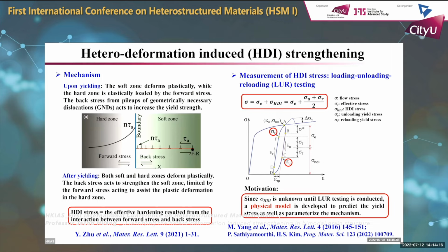In practice, the contribution of such HDI stress to the overall flow stress can be estimated by the loading, unloading, and reloading (LUR) testing. But in this study, we have some motivation. We still think it is necessary and meaningful to develop an analytical dislocation model with more physical meaning to predict the yield stress as well as to parameterize the mechanism.